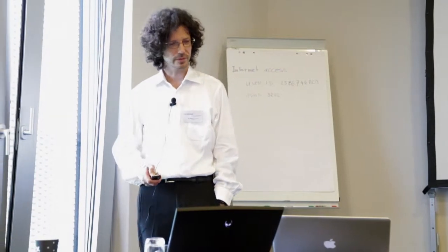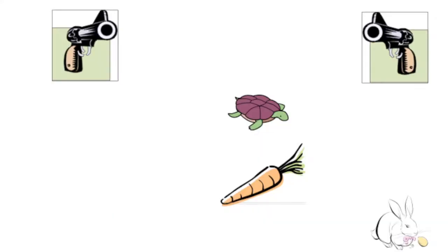And the question is, if you do something on the way back to perturb the behavior of one of them, for example introduce a little carrot. And then on the way back, the rabbit is going to be slowed down, and your final measurement is going to show a difference, which is that somehow the rabbit has been perturbed by something, and this something in the experiment of the TRAPDOR is the irradiation of the aluminum ions. So in this sense, you're probing whether specific protons in the polymer are close or not to the surface of the aluminum.